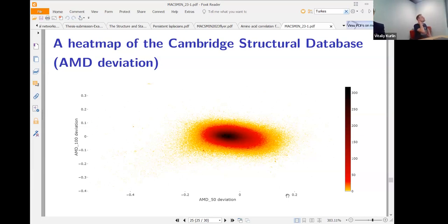But there is a problem with continuity, because six exact neighbors could become different under perturbation. That's why there is extra smoothing on the PDF. Instead of this extra smoothing, we apply Earth Mover's distance to get a continuous metric. So we don't use any smoothing. We keep the invariant consisting of discrete values.